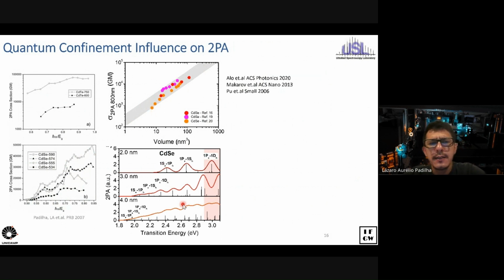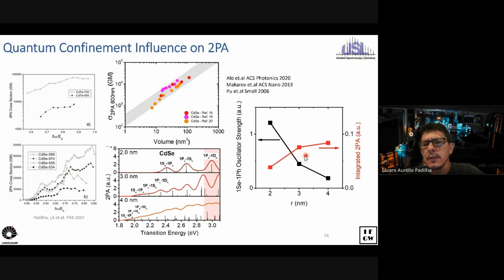And the reason for that is that even though every single transition increases, so you see the magnitude of a single transition decreases when the size gets bigger. In other words, it increases as the size gets smaller. If you integrate over the transitions, when you go to the continuous or quasi-continuous spectral range, we see the other way around, because you have a drastic reduction in the density of states when you make the quantum dots smaller. So there's a trade-off between increasing a single transition and reducing the density of states, which makes, at the end of the day, two-photon absorption in principle not necessarily enhanced in nanomaterials.